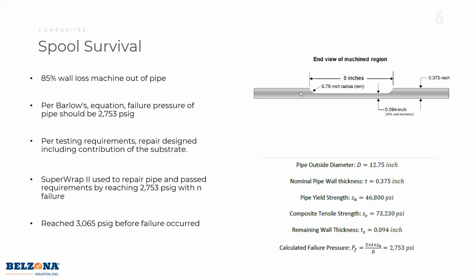So we have a test specimen where 85% of the wall is removed via machining. The original pipe with all of its wall should be able to hold 2,753 pounds according to Barlow's equation. The job of the composite is to make sure that even though we have 85% wall loss, if I wrap it with my composite, it can still handle the original burst pressure of 2,753.